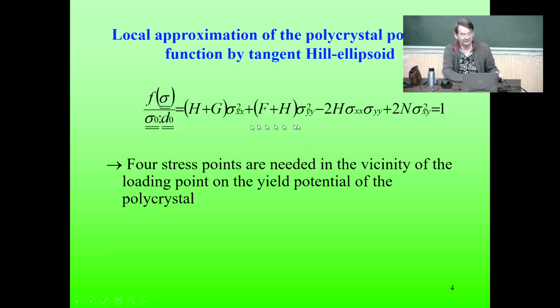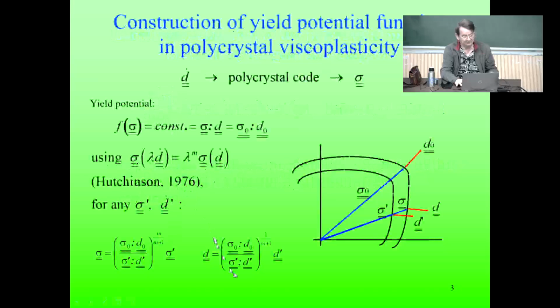In this format, we define the yield potential so that F of sigma, the yield potential function, we divide its value by the reference value, and then we get the so-called Hill ellipsoid, which is going to be equal to 1. So it is the normalization. This is the equation which is relevant here. But it is done in such a way that the previous sigma 0, D0 condition is satisfied, so that whatever stress state we obtained in the polycrystal simulation, we are going to jump it on the equipotential yield potential of our reference one.